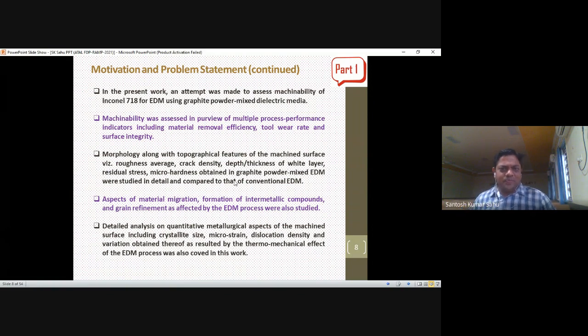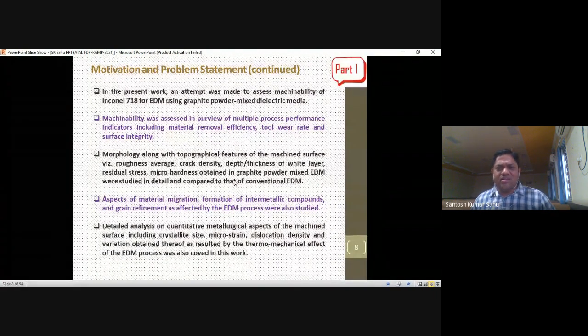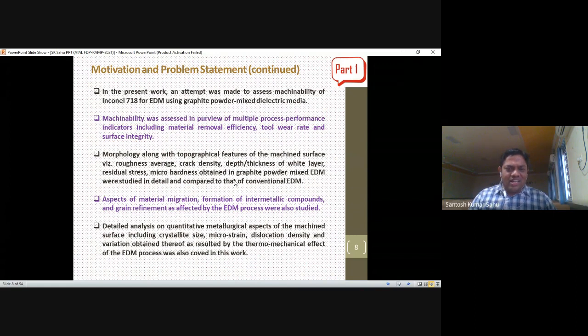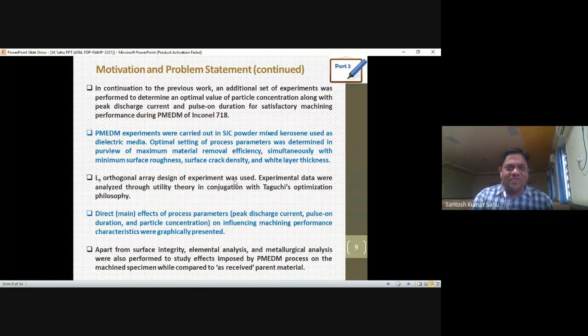So in part one, we also check the machinability. Then we can take care of the morphology and topology of the machined surface: roughness, crack density, white layer thickness, residual stress, microhardness, everything we can discuss. Then aspects like material migration, formation of intermetallic compounds, and grain refinement as affected by the EDM process. You also have to take care of these. Then a detailed analysis of the machining process, and you have discussed all that.